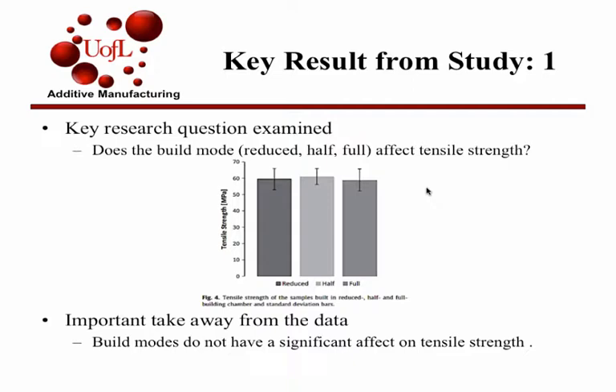Really what this graph is showing is that there was not a significant statistical difference in tensile strength from the differences in build mode. The machine that they used specifically for this, like I said, is the EOS P800. That machine is unique in the sense that you can have these three different build modes. The important takeaway is that it didn't have a huge effect on the tensile strength at all. So you could use any of those modes and expect to get the same strength out of it.